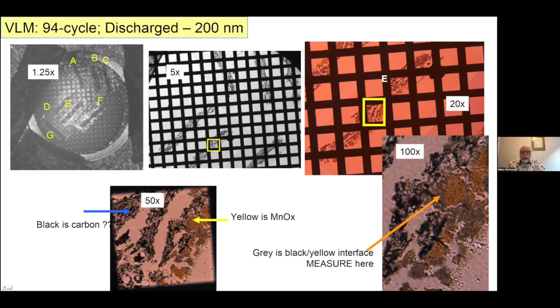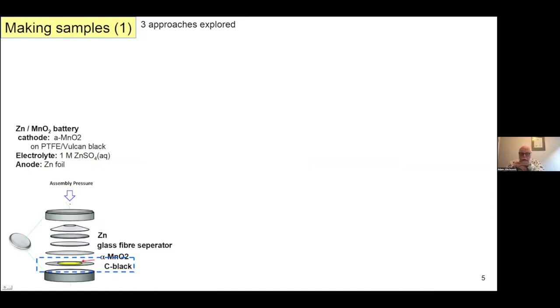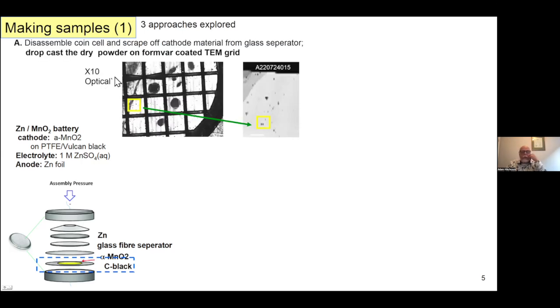So I want to compare two different approaches that we did to measure this system, and it's a bit of a lesson there. These samples were made by members of Drew Higgins' group using a coin cell. You've seen these, they're the way that you can get lithium and other battery technology for various devices. It's a stack of various materials: the zinc anode at the bottom, the carbon electrical contact of the cathode, and then this manganese dioxide material intermixed with the carbon black. There's a glass fiber separator, and the whole thing is compressed to get good electrical contact and be able to do electrochemical testing.